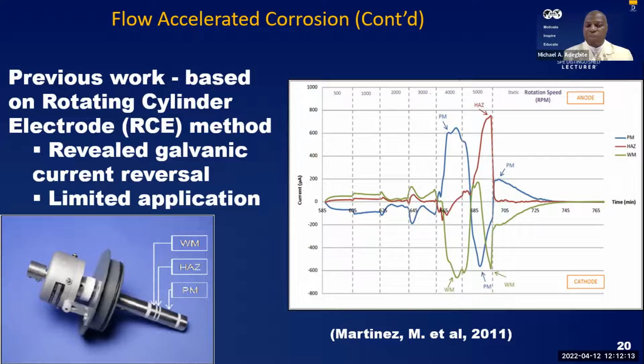So selecting each of these phases, the weld metal, the heat affected zone, and the parent metal, looking at them separately and joining them when necessary, we see that one there is a reversal. There are times a component behaves in an anodic manner, that is, goes into solution, and there is a time it's protected. And this again is under inhibition. So it means that the inhibitor is inconsistent. And there are some things that will lead to that. We'll be looking at that as we go on, please.